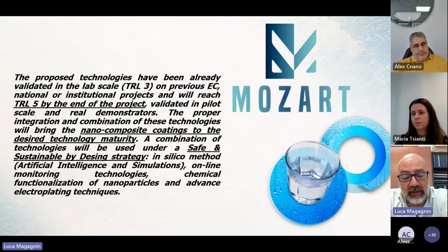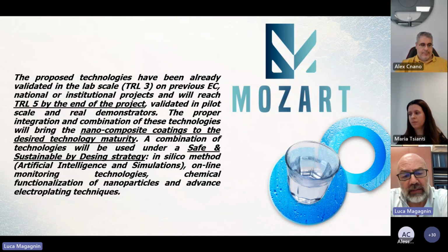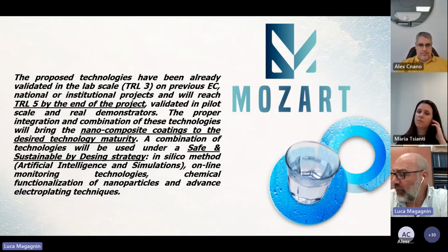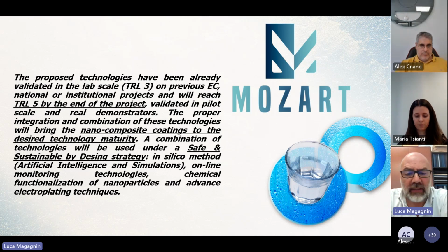The other part is, let's say, I mentioned briefly the functionalization of the nanoparticles, and the advanced electroplating techniques, mainly meaning pulse plating, for instance, and the functionalization of the particles in order to achieve a very good dispersion of the particles, but that is part of the formulation. Important is the online monitoring technologies, because if we want to really upscale and to be market ready for any composite process based on electroplating, we need a tool or system to control very well the presence, the amount, the distribution and the dispersion of the particles in the liquid, because this is really connected to the amount of particles that we are able to co-deposit in the matrix, and also to their distribution in the coatings, and so at the end correlated to the performances of the coating.